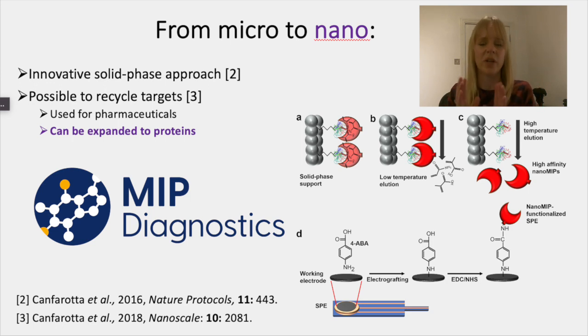And in brief, you can have a look at the papers below if you want to know more about it. Here, rather than eluting off your target, you begin by attaching your template to a solid phase, you polymerize around it, and then you elute off the polymer material instead. And the big advantage of that is that you can use your solid phase as an affinity medium. So you end up with very homogeneous particles, and only the ones that have a very high affinity, which is what you will get when you do this temperature elution.